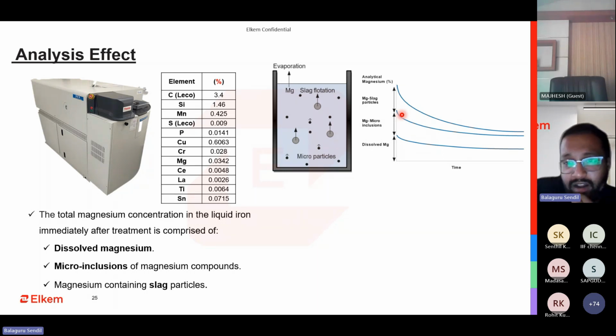So when you are doing ductile iron treatment, if you're holding the metal for long after treatment, you see a bit of slag being generated. You can remove that and throw it out and continue. The only thing is that these Mg inclusion sites will be there. You need to have a correct amount of inoculant, a capable inoculant, depending upon your casting geometry, to activate that to come to a correct size nodule.